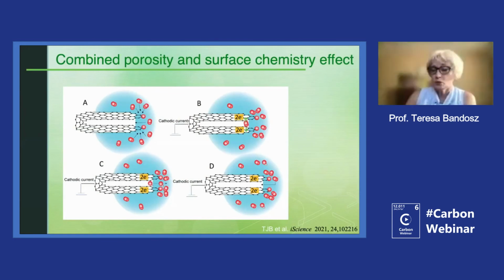But with the new results, we thought that, okay, the pores are important, and as we found also before, the hydrophobicity is important, but not only the hydrophobicity in the pores, but also the hydrophobicity of certain groups on the surface, because we might have oxygen groups which are hydrophobic, ethers, for instance. So what happened? We have oxygen in the electrolyte, and those groups attract oxygen. So not only the pores, but also the groups attract oxygen. And then we have the reduction in the pores, and the oxygen is ready to enter again. So it is some kind of concentration at the pore entrance. It is, of course, our hypothesis.